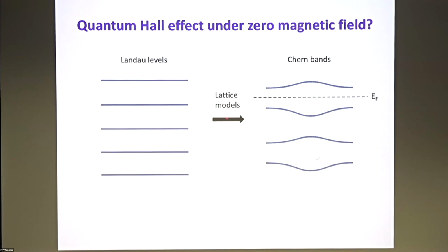electron gas without a lattice, if you can cook up an appropriate lattice with the right amount of imaginary or complex hopping, then you can actually get a series of flat Chern bands that look quite similar to the Landau levels. And if you put your Fermi energy filling one of the Chern bands, you get the Chern insulator and the quantum anomalous Hall effect as have been predicted. And if you actually put another time reversal copy of these flat Chern bands, you will get the 2DTI or the quantum spin Hall insulator in its simplest form. And that was found by Kane and Mele, 2005, and also by Bernevig, Hughes and Zhang, 2006, around the